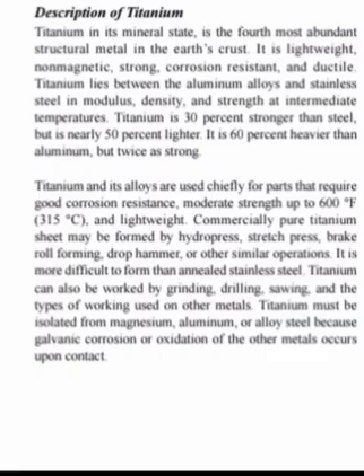Titanium is 30% stronger than steel, but is nearly 50% lighter. It is 60% heavier than aluminum, but twice as strong. Titanium and its alloys are used chiefly for parts that require good corrosion resistance, moderate strength up to 600 degrees Fahrenheit, and light weight.